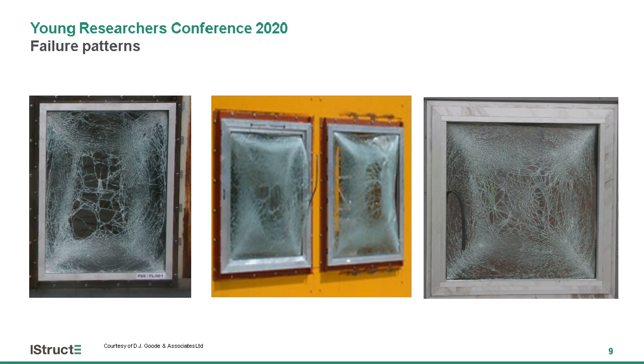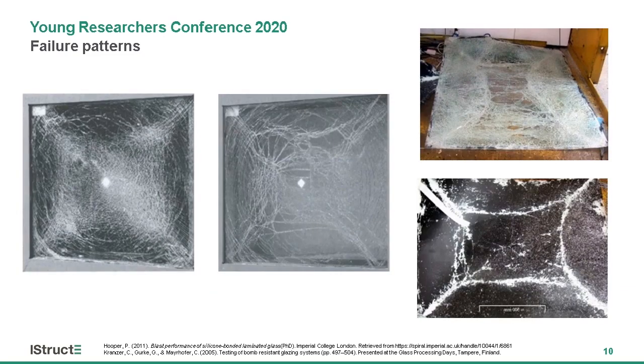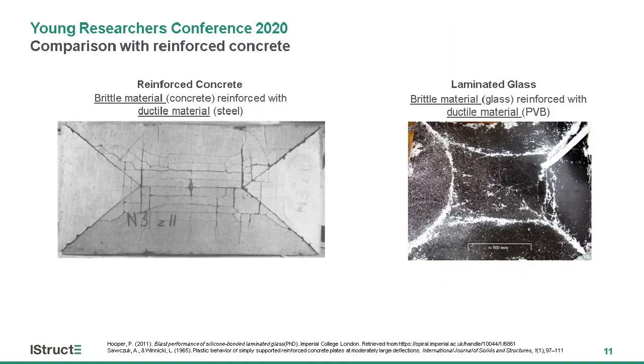The blast response of these panels, however, is complex and often requires assistance from blast testing to validate designs. Most of the existing analysis methods assume a pure membrane response of the PVB in the post-fracture stage. This, however, is in contradiction with a failure pattern repeatedly observed in blast tests that resembles a yield line pattern.